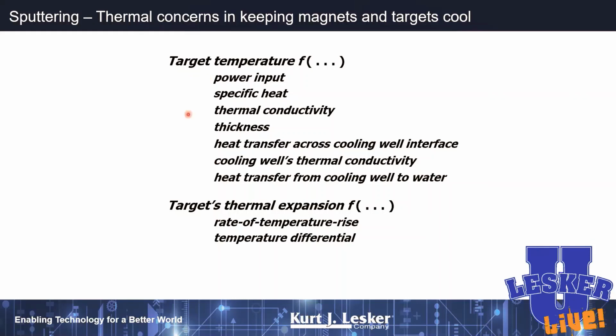You need to think about the thermal conductivity of your target. Again, thicker targets are harder to cool than thinner targets. You've got to think about the cooling well and whether you've got good thermal connections to the target itself. If you think about the target's thermal expansion as it gets hot, it's going to grow, and if it fits tightly into your cathode, that expansion may cause it to crack.